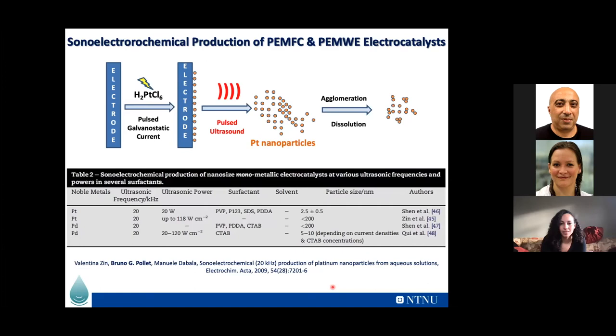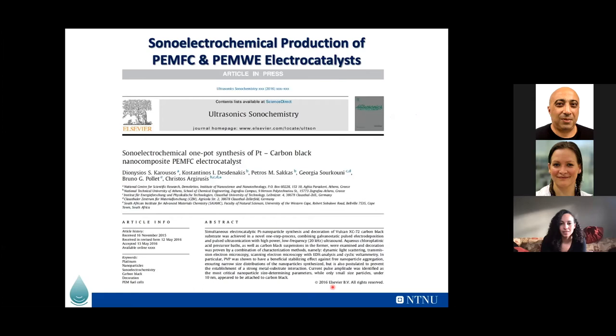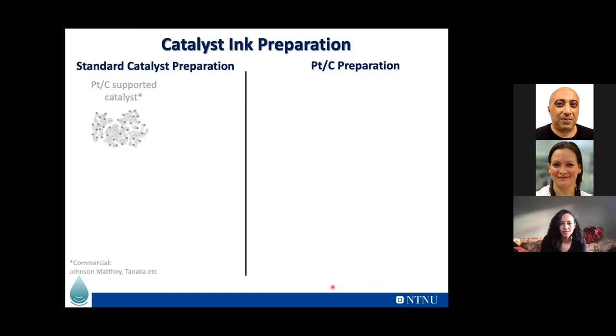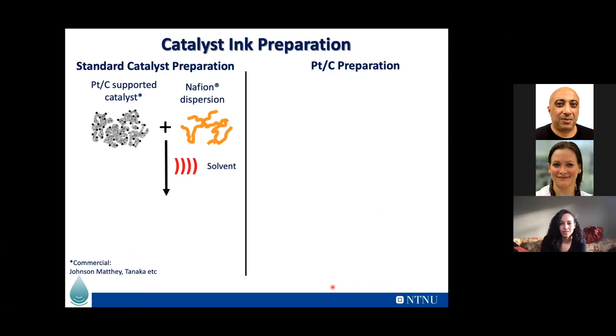Then with some teams in Germany and in Greece, we thought, why not look at having this one-pot synthesis? Okay, so having your platinum, carbon and your ionomer all in one. So I'm going to do this quickly here. This is the standard catalyst preparation. You get your platinum on carbon supported catalyst. You mix it with your Nafion, which is your ionomer, and you are using a solvent. It could be IPA or another type of solvent, a blast of ultrasound, and you're producing your catalyst.